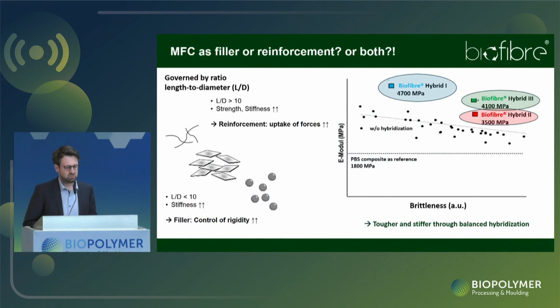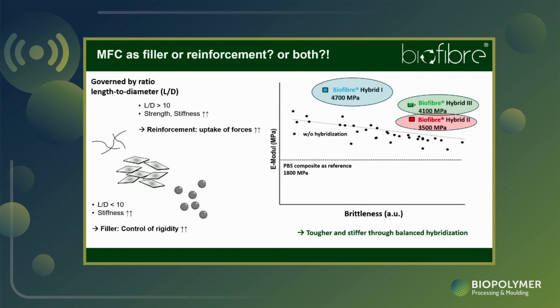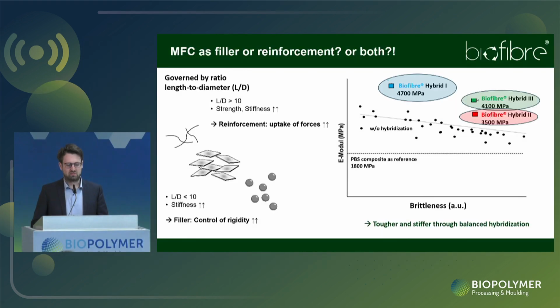So talking about nanofibers, as this is envisioned to be one solution for those issues, we looked into what we have already in stock, and we saw that natural fibers can be divided into being a reinforcement to bioplastics or just a filler. It's largely dependent on the aspect ratio. This means that the length to diameter ratio has to meet a certain level, and then you can talk about the strength imparting and stiffness enhancing reinforcement, let's say, and you can uptake forces during the application.